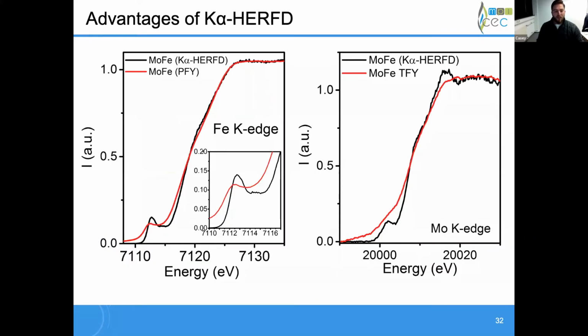And just as an example of this line sharpening effect, we can see for iron K-edge that we have two pre-edge features that come out of an otherwise very broad single pre-edge feature from the partial fluorescence yield. And even more powerfully in the molybdenum K-edge spectra, we go from something that looks kind of like a broad sinusoidal absorption spectrum to something with a distinct pre-edge feature, rising edge feature, and a white line feature. So this really can give us a lot more information about the system, particularly at molybdenum, than we can get out of partial or total fluorescence yield experiments.